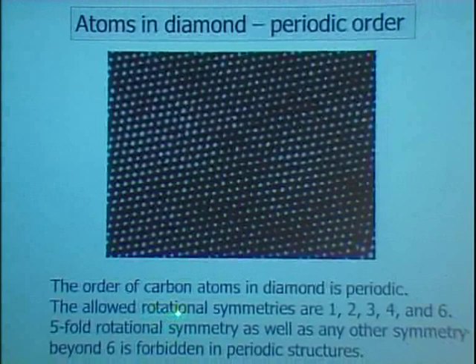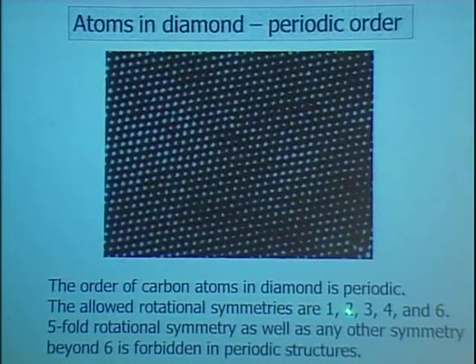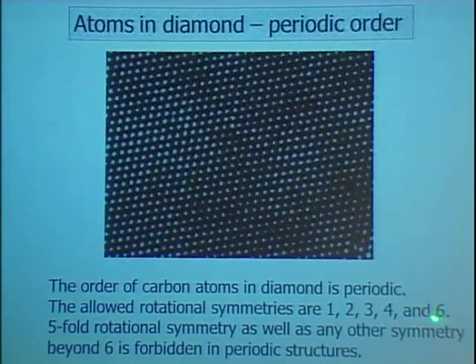And the rotation symmetries that are allowed are 1, 2, 3, 4, and 6, no 5, and nothing beyond 6 are allowed in the real space. This is because, as I said, of geometrical reasons. This is in a periodic lattice. No 5-fold rotation symmetry and nothing beyond 6.